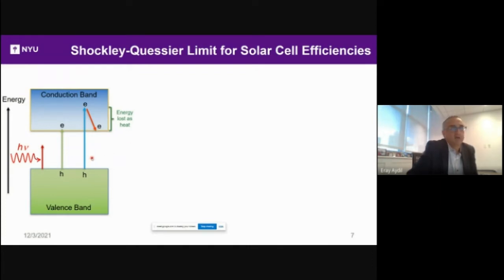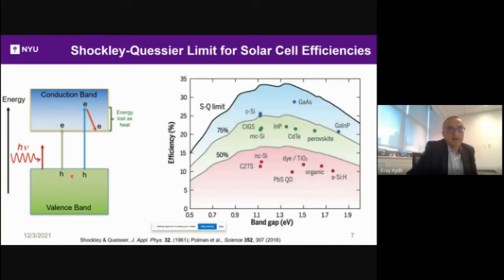So for a given semiconductor that you're going to make a solar cell out of, if the band gap is too large, then you throw away a lot of the photons. If the band gap is too small, then you lose a lot of the energy as heat. So there is a happy medium, and the calculation was done back in 1961 by Shockley and Queisser, and they showed that there is a maximum. And so these are all the solar cells that have too high of a band gap. These are all the ones that have too low of a band gap.